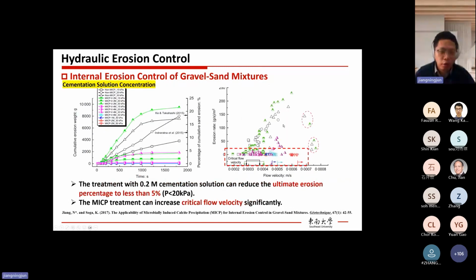Then we want to know what the key factors are that affect the erosion control effect of MICP for gravel sand mixtures. So firstly, we've looked at the cementation solution concentration. And from this graph, this is the erosion rate versus time graph. You can see that the black one is the untreated samples. The green one is the low cementation case. The pink one is the moderate cementation case. Then the red one is the heavy cementation case.